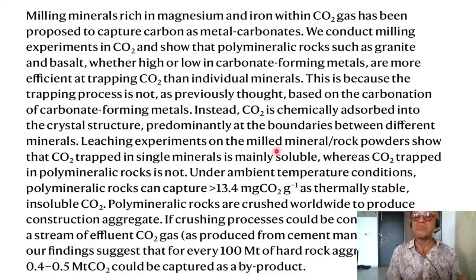Leaching experiments on the milled mineral rock powders show that CO2 trapped in single minerals is mainly soluble, whereas CO2 trapped in polymineralic rocks is not. Under ambient temperature conditions, polymineralic rocks can capture greater than 13.4 milligrams CO2 per gram as thermally stable insoluble CO2. Polymineralic rocks are crushed worldwide to produce construction aggregate. If crushing processes could be conducted within a stream of effluent CO2 as byproduct from cement manufacture, for example, our findings suggest that for every 100 million tons of hard rock aggregates sold, 0.4 to 0.5 million tons of CO2 could be captured as a byproduct.